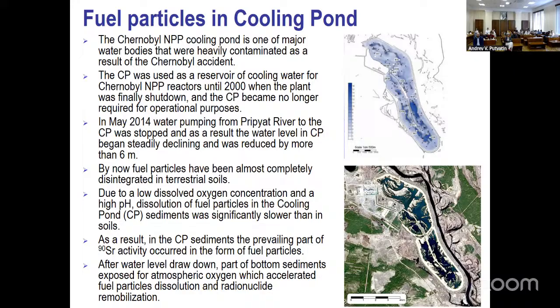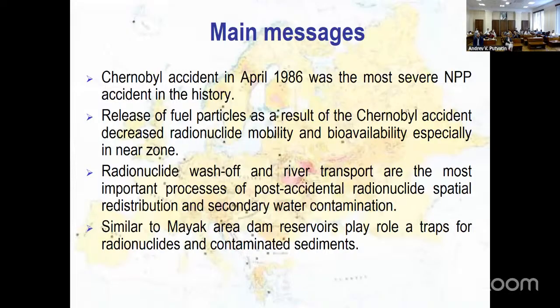By now, fuel particles have been almost completely disintegrated in terrestrial soils. However, due to low dissolved oxygen concentration and the high pH, dissolution of fuel particles in the cooling pond sediments was significantly slower than in soils. As a result, in the cooling pond sediments, the prevailing part of strontium-90 activity still occurred in the form of fuel particles. After the water level dropped, part of the bottom sediments was exposed to atmospheric oxygen, which accelerated fuel particle dissolution and radionuclide remobilization. So, main messages about Chernobyl.